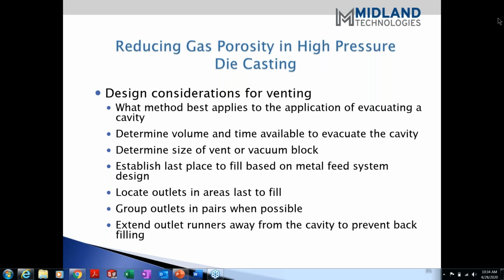I've done it intentionally. I've tied two overflows together, and in most instances, I end up pushing metal back into the casting. Subsequently, I've introduced air back into the casting and just moved from one to the other. Again, not always. So I encourage people not to necessarily tie those in. It's very convenient to capture the overflows and scrap material, but it is also detrimental to the ability of the evacuation system to function properly. Next slide.